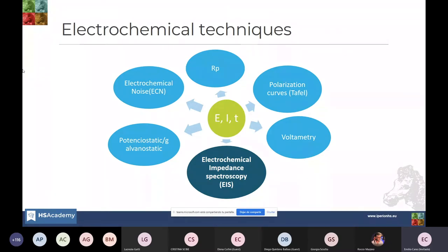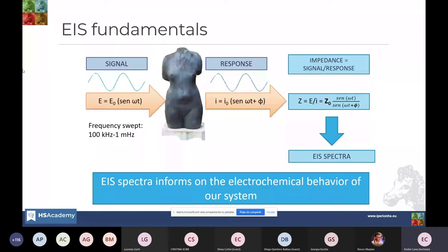But I would dare to say that probably the most popular one is electrochemical impedance spectroscopy, better known by the acronym EIS in English. So I will focus on this technique, which is based, as you can see in this slide, on the application of an alternating current signal. We apply an alternating current signal, and we change the frequency we are applying, and we make a frequency sweep, typically from 100 kilohertz or 1000 kilohertz down to 10 or 1 millihertz, depending on what we are measuring.